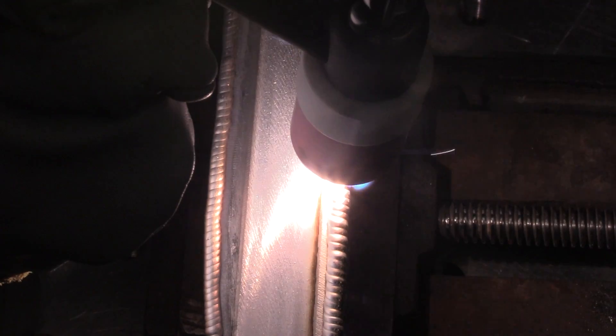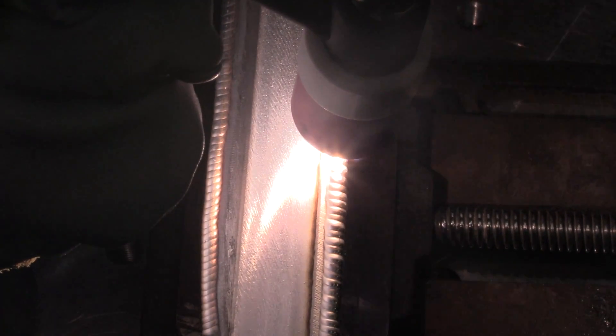That's a technique I use on dirty aluminum, oil soak castings, you name it. On any kind of aluminum, I just want to make sure I get a nice shiny clean puddle before I proceed. Notice that I've got a tapered tip on the electrode also. That's mainly for good crisp starts because I'm not using much amperage here, especially on the very corners when I light up. I don't want the arc going everywhere.